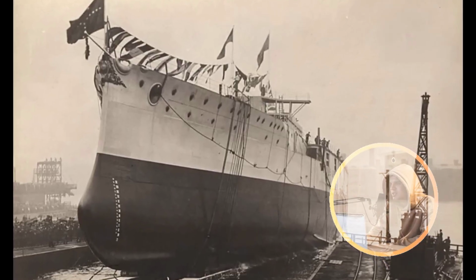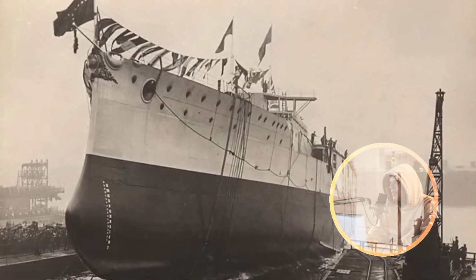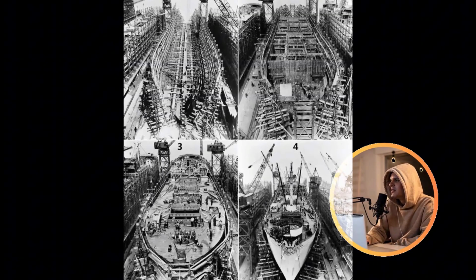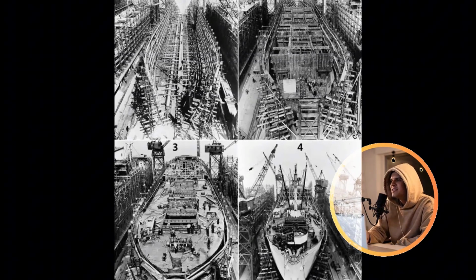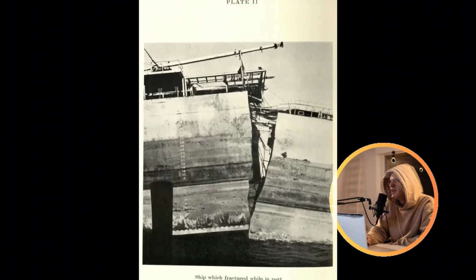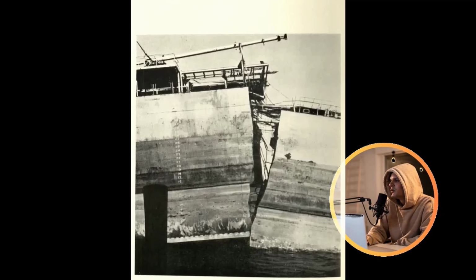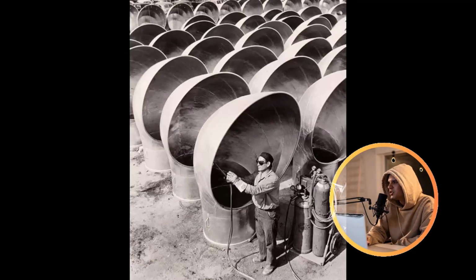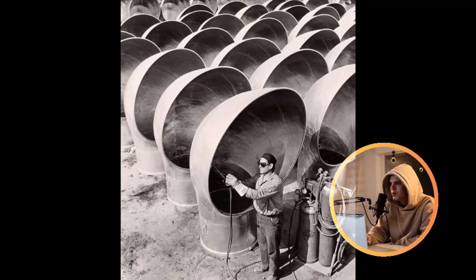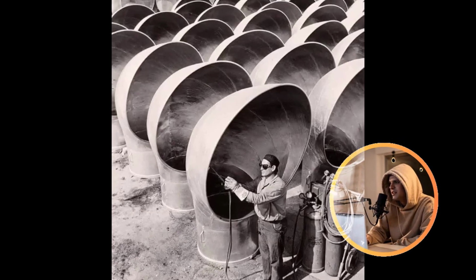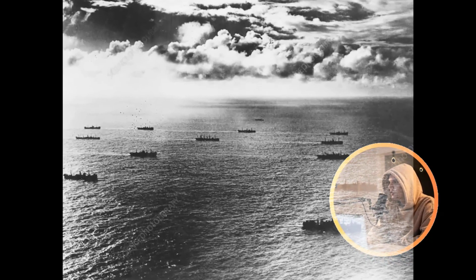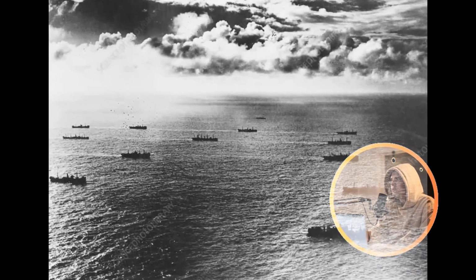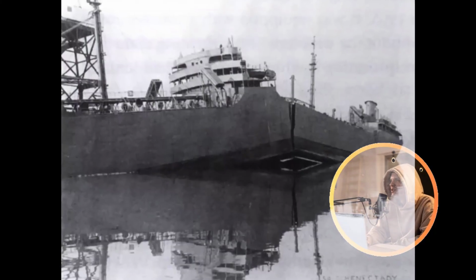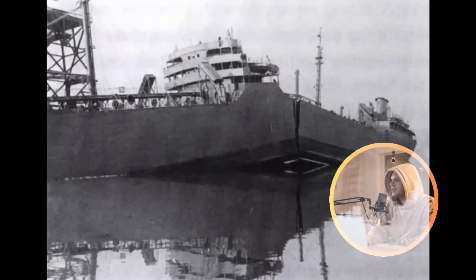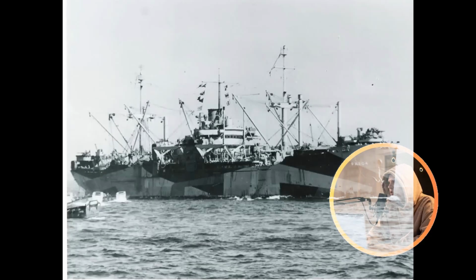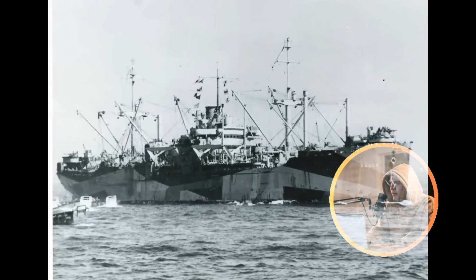The very composition of the steel itself underwent a significant transformation. Kaiser's astute metallurgists specified a new alloy designation, meticulously formulated to possess dramatically improved low-temperature toughness, a critical property for ships operating in frigid waters. The carbon content was subtly reduced, while the manganese content was judiciously increased to enhance ductility. Small, yet impactful, additions of nickel, a notoriously expensive and heavily rationed metal typically reserved for armor plating, were rigorously justified. Demonstrable evidence showed that even a modest 0.25% nickel content dramatically bolstered the steel's resistance to brittle fracture.